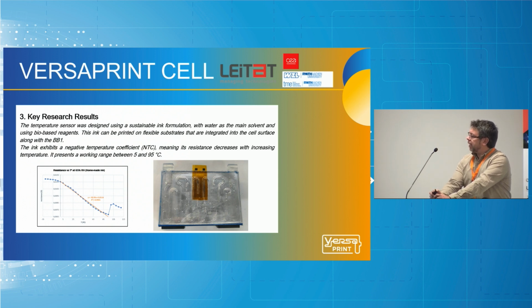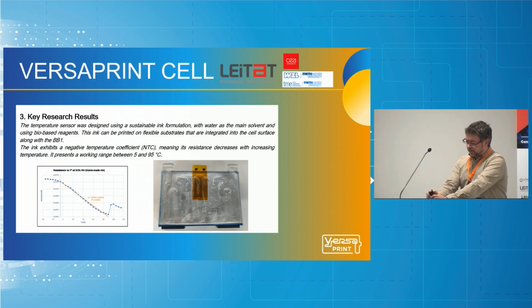We observed that the ink exhibits a negative temperature coefficient, meaning the resistance decreases with increasing temperature. And there are some limitations for now with these sensors. It presents a working range between 5 and 95 degrees. We have some problems with humidity at the extremes of this working temperature range.